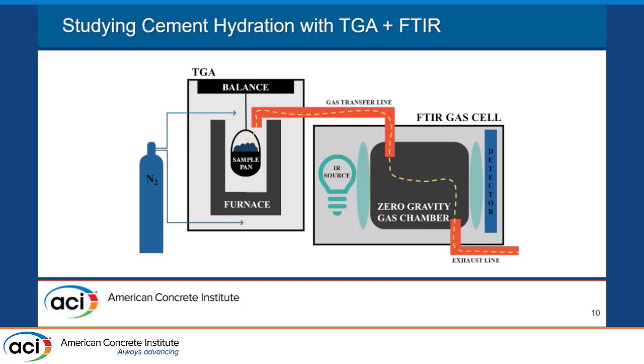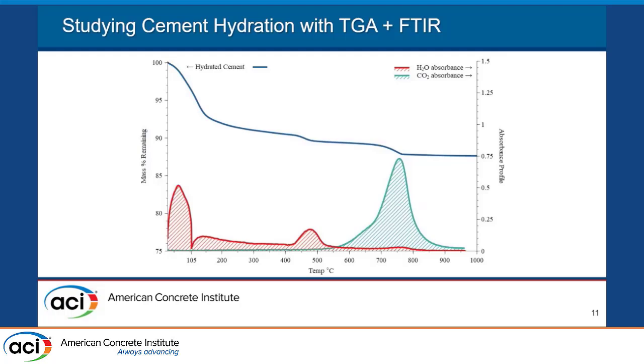Biochar has a lot of volatile content and will begin to decompose additionally above its production temperature. So this kind of muddies the picture of our mass loss. We were seeing really high mass losses with our cement paste samples and trying to figure out, is that increased hydration? Is that the biochar decomposing? What's going on? So we employed TGA-FTIR, which basically just takes the gas that's decomposing, tells me what kind of gas it is, and then we can back calculate from there.